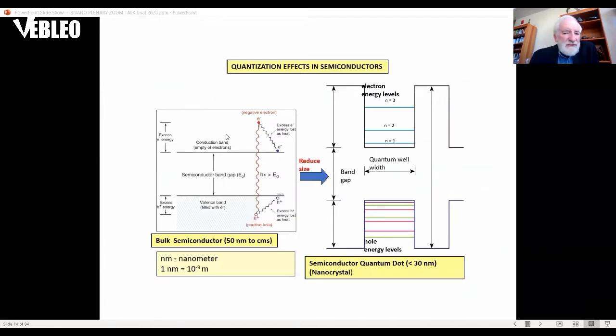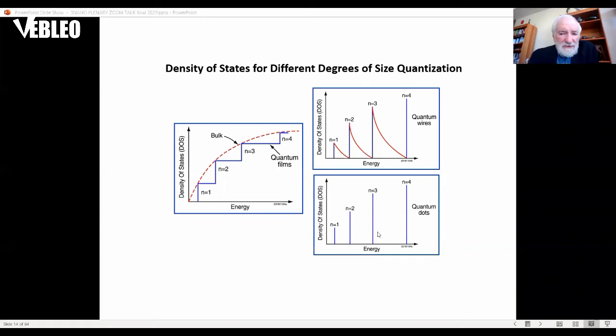Now the quantization is just shown here. This is the bulk material with a bulk band gap, but when you reduce the size below a size where the diameter of the particle is less than twice the Bohr radius of the material, which is a fundamental property of that material, the Bohr radius of the electrons and holes, then you get, instead of a quasi-continuous distribution of energy states that form the conduction and valence bands, individual discrete levels in the conduction band and in the valence band. And sometimes you get a double set of levels, say, in the valence band because of the degeneracy of the band structure.